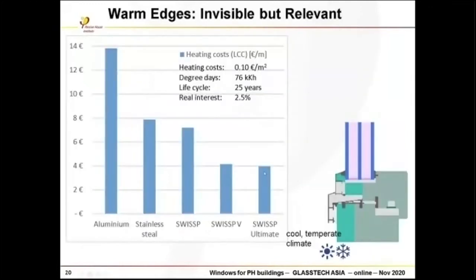Well, the glazing rebate or the spacer here at the glass edge is very important. So if you go for aluminum, the very bad windows, it's not a good idea. Stainless steel is better. And here you see the product Swiss Spacer and the newer development Swiss Spacer Ultimate. With that, you can get a very, very good thermal quality at the edge with a quite slim design.